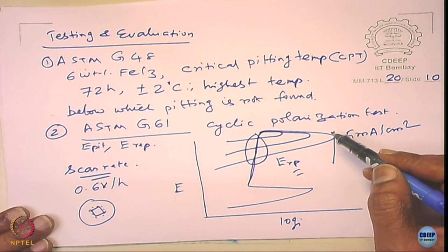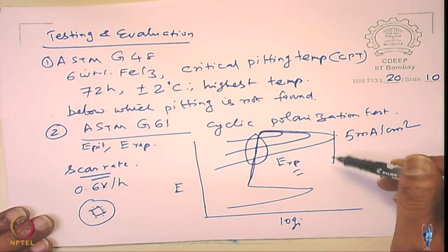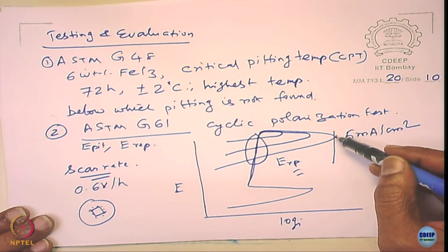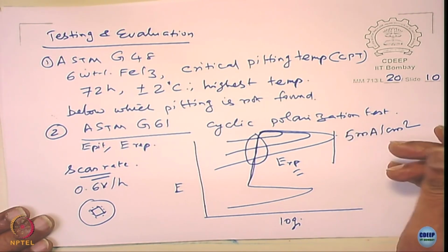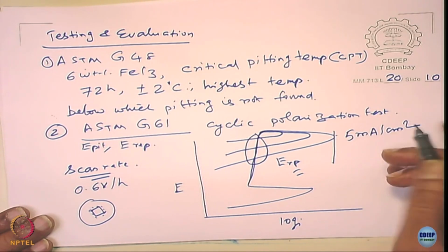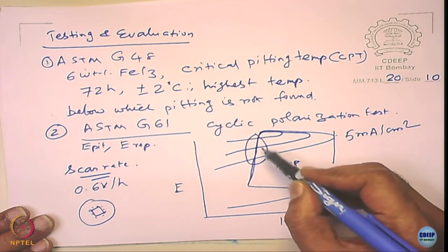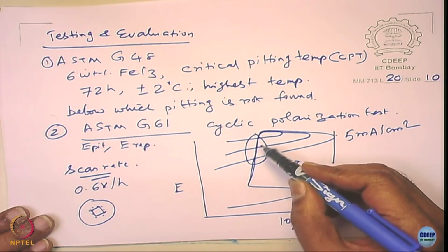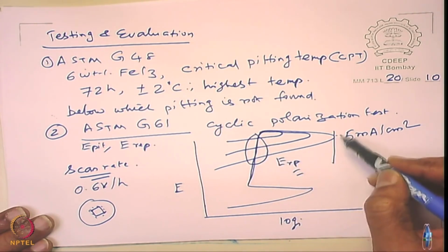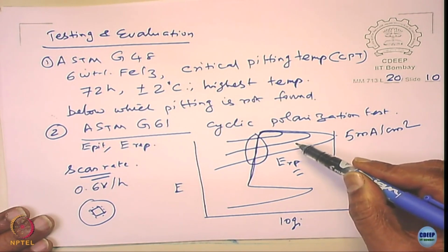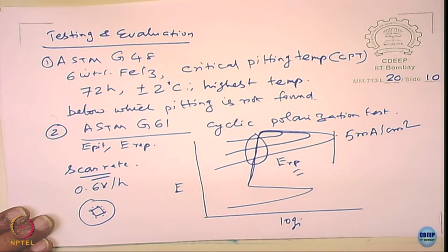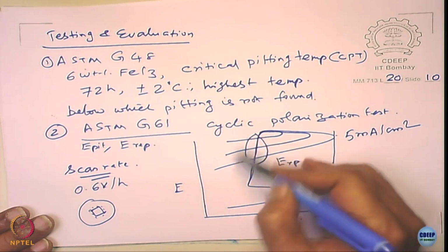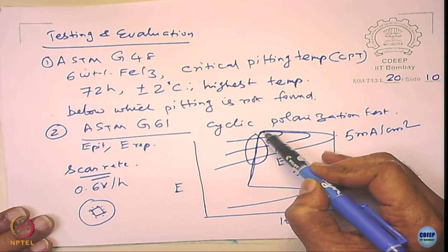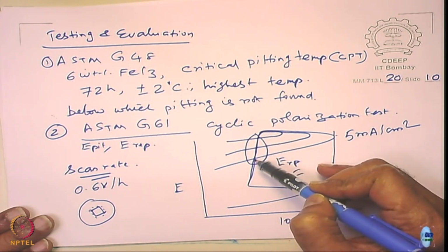In fact, work was done in Southwest Research Institute by Narasi Sridhar and group, where they have shown that there is a critical pit depth beyond which it is not going to affect the repassivation potential. So that means you need to follow this standard meticulously, without which you may get a different ERP value, which is not an indication of the pitting growth resistance tendency of the metal actually. Please look at this, this talks about pitting initiation, and this talks about the pitting repassivation here.